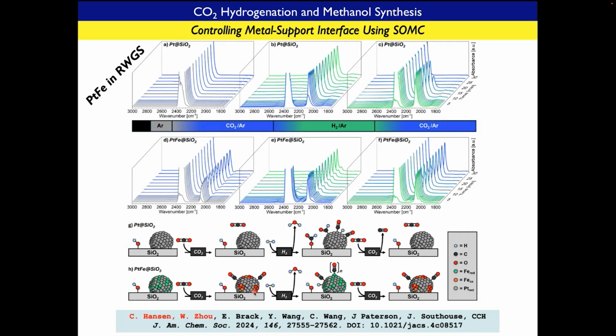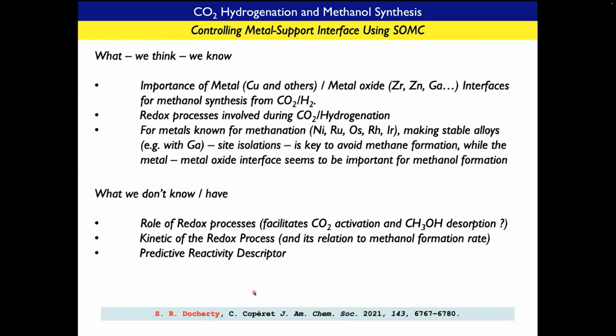water gas shift reaction. So I hope I've convinced you that with our approach, we can generate many complex systems. Today, having explored more than 100 catalysts by this approach, though I didn't show you all the details, we can see that very likely metal oxide interfaces play a very important role in driving methanol formation. We also see that this involves redox processes. Very likely the metal remains metallic and the promoter element like gallium always switches between gallium and gallium oxide.